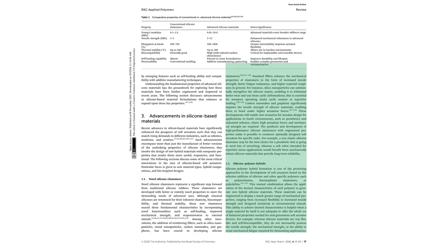A key innovation has been the addition of reinforcing fillers. Nanoparticles of silica, for instance, can substantially strengthen the silicone matrix, making it more resistant to wear and tear from cyclic deformations, essential for actuators in constant motion. Other fillers like carbon nanotubes and graphene can significantly improve tensile strength, enabling the actuators to function under higher forces. These developments allow for the design of actuators for harsh environments, like industrial robotics or prosthetics, where high actuation forces and mechanical strength are required.